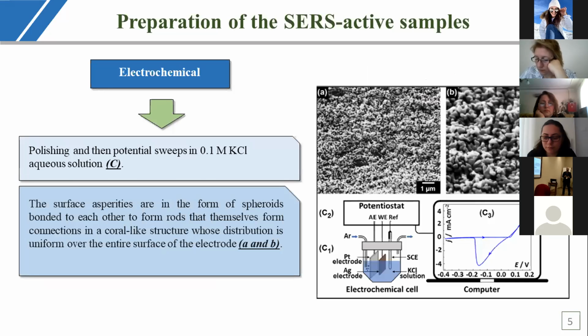In the first method, before the electrode deposition step, a preliminary roughening procedure is applied to the electrode. The silver surface is polished and introduced into an electrochemical cell containing potassium chloride aqueous solution in order to achieve 3 potential sweeps between -0.4 and 0.2 volt. The SEM images after the activation process reveal the presence of asperities in the form of spheroids bonded to each other to form rods that themselves form connections in a coral-like structure whose distribution is uniform over the entire surface of the electrode.